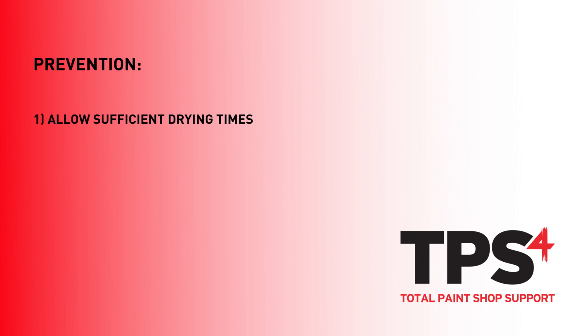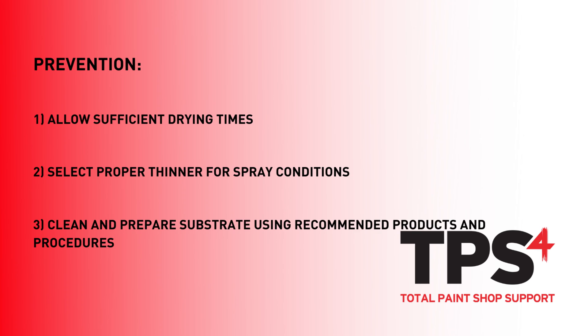To prevent these blisters happening in the first place, you will need to allow for sufficient drying times, select the proper thinner for spray conditions, and clean and prepare the substrate using the recommended products and procedures. If wet sanding is preferred, you should allow enough time for the moisture on the surface of the coating to evaporate.